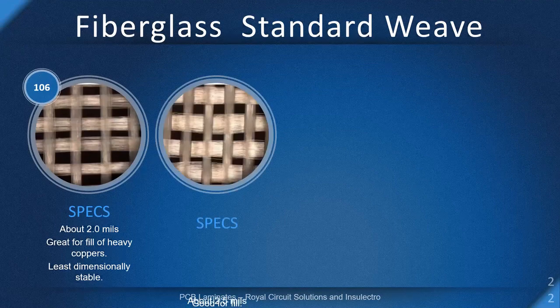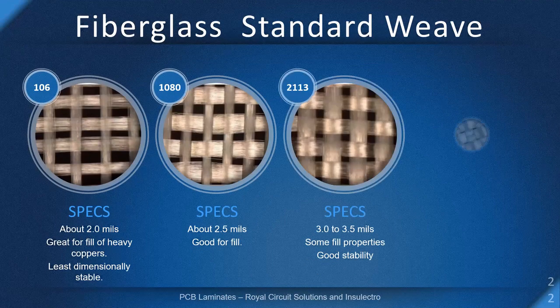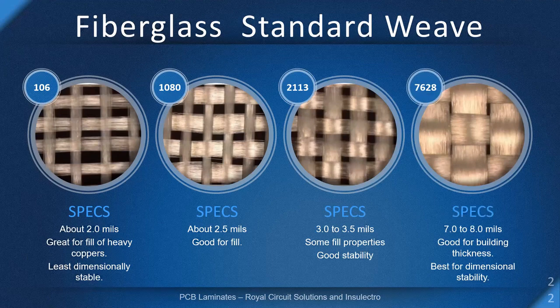So again, designers and OEMs don't need to become PCB or material experts. I just want to give you guys a flavor of some of the stuff that we work with. These are standard fiberglass weaves. So in other words, the glass fabric can vary in thickness, and these are building blocks to make a complex PCB. Could be the thicker glasses like 7628 if it's a simple double-sided board, or it could use the 106 if the board layer count's high and you need thin layers, or if it has thick copper. And Royal Circuits does probably more thick copper work than many other fabricators, so they use this as building blocks for filling the thick copper circuits.